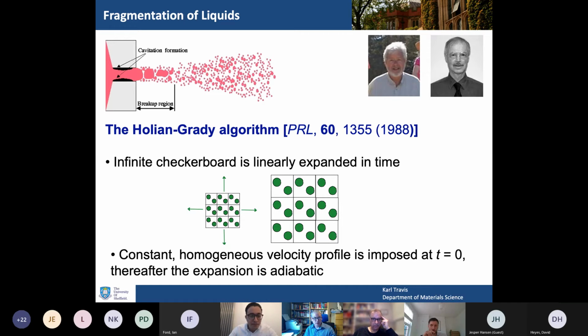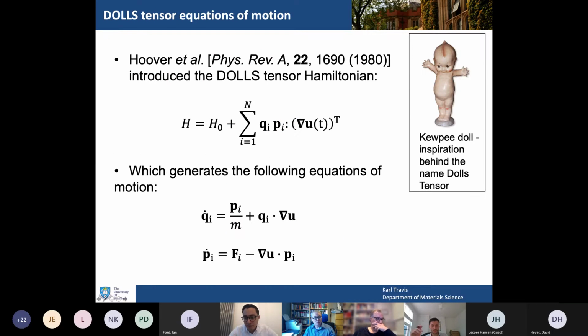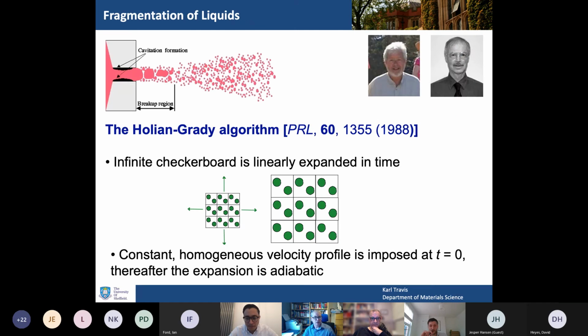You can stretch a liquid. In other words, you can place a liquid under tension or negative pressure. You can do that by, for example, isochoric cooling into the negative pressure region. But once you've done that, it'll become metastable with respect to cavitation. Okay, so you can get interesting phenomena, and the liquid will break up into droplets. Some of these droplets may be solid, so you get a mixture of solid, liquid, and vapor. And this has got interesting applications. One particular application is in dumping of fuel from aircraft.